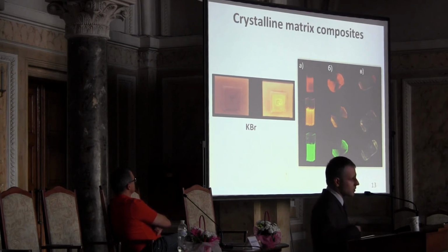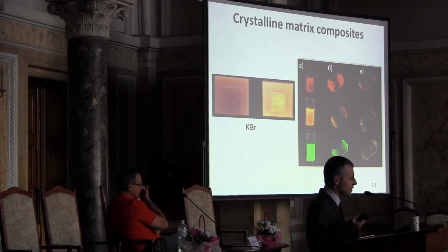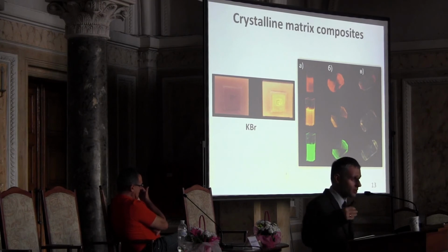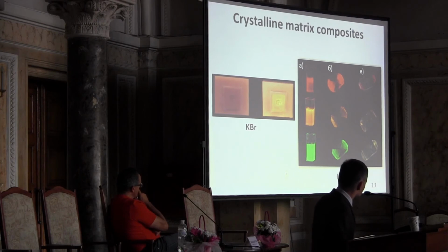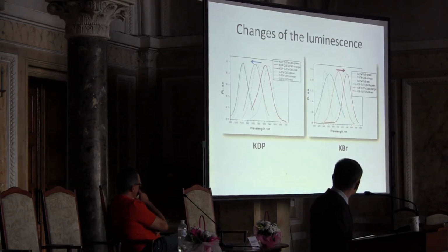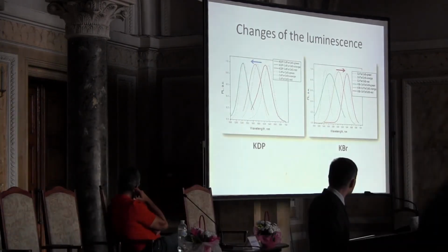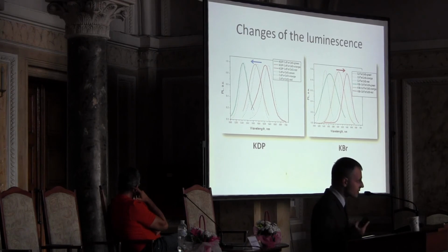Or you can do it with sodium, potassium dihydrogen phosphates, which is a non-linear optic material, and then you come up with this kind of fancy structures due to the specific sorption of negative nanoparticles on the growing surface of potassium dihydrogen phosphate growing crystal. And actually, for both matrices, two different behaviors occur.